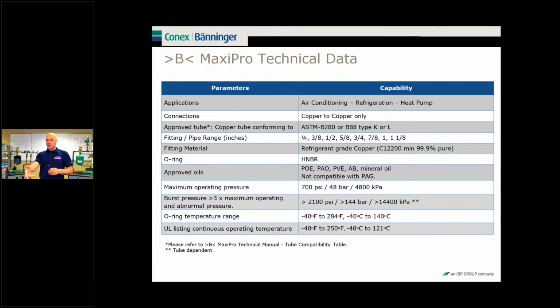We will work with roll copper that meets that ASTM B280 or B88 standard, and with rigid copper. We have a 2100 PSI burst pressure, so that's 3 times the working pressure. And again, the working pressure is 700 PSI. That may be important to you later. Okay, the O-ring range is -40 to 284, but you're going to write down the UL number because you're going to need that later. The UL is -40 to 250 degrees Fahrenheit. That's going to be an important number to you later.